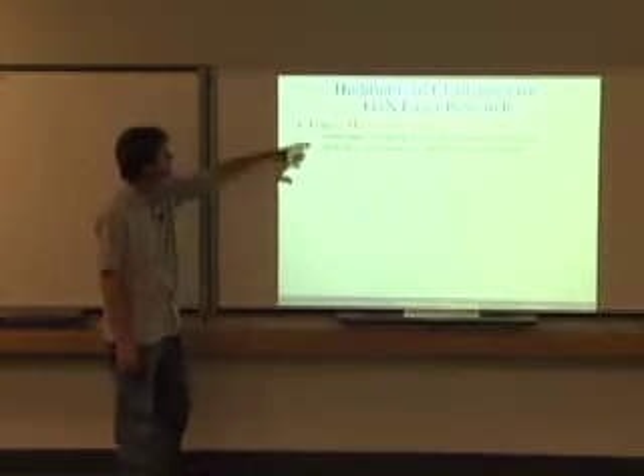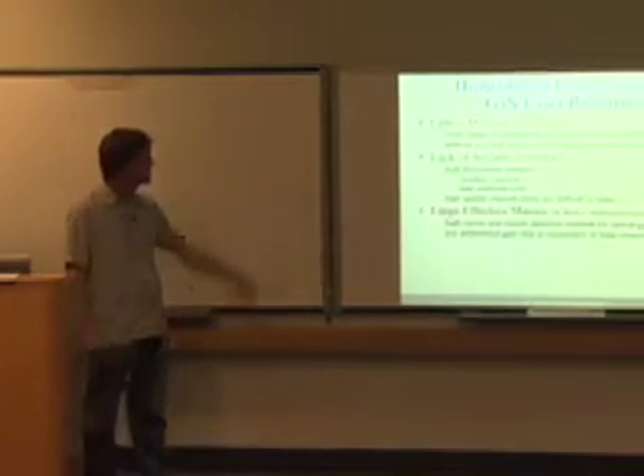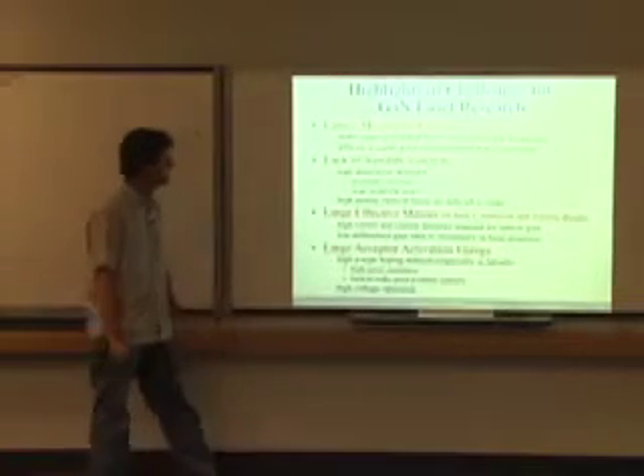So highlights of challenges for gallium nitride laser research include: it was a lattice mismatch system, so it limits the range of cladding layers and compositions and thicknesses that you could work with. Lack of a suitable substrate, of course everybody knows this. High dislocation densities, reliability concerns, and high quality facets are difficult. Large effective masses, both in the conduction and valence bands, so this leads to very high carrier and current densities required for optical gain. Low differential gain. Large acceptor activation energy, so this made it a struggle to get good P-type doping, especially for both series resistance as well as ohmic contacts, and it led to very high voltage operation.